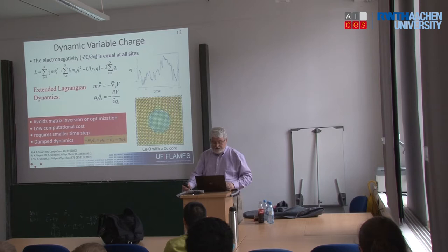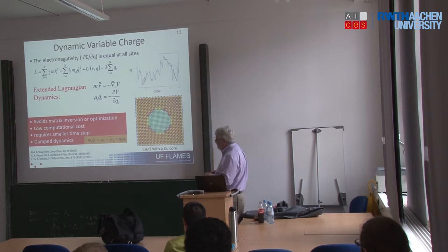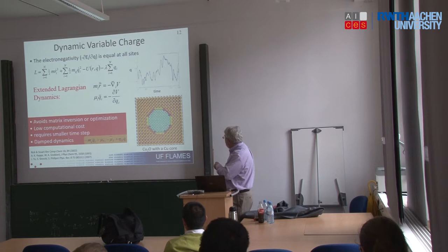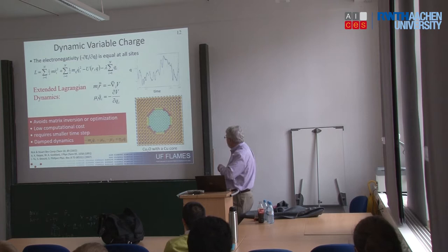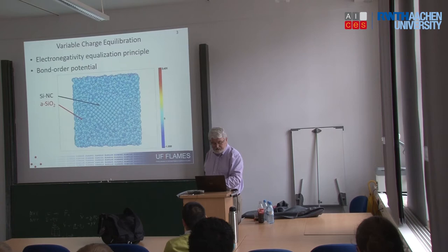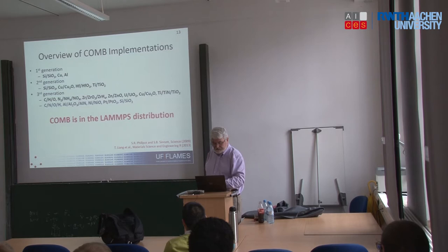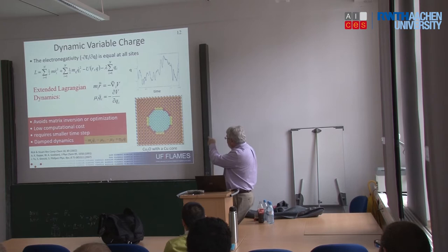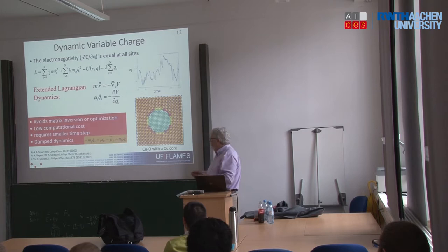It's the same. So this is copper inside Cu2O. The color scheme is what we had before. This bluish color is charge neutral, and then these are the oxygens, which are strongly negative charge. These are strongly positive charge, and we're seeing the variation of the charge around that core. And this is something which the system, again, just by running this algorithm, went through and determined. So the coppers aren't intrinsically different from each other. They just figured out the local environments and respond differently.